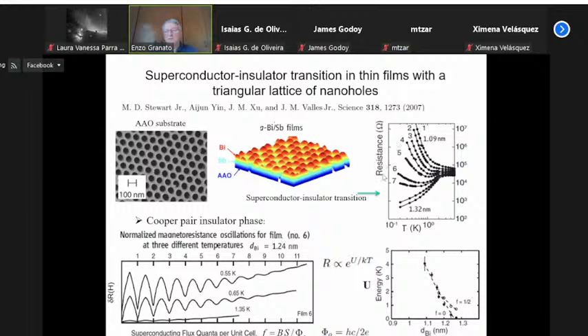Now, on the insulating side, for example sample 6, if you look at the resistivity as a function of magnetic field, this figure in particular is for zero field. If you now apply a field and look at the resistivity of the sample in the insulating phase, you see that this resistance oscillates. The oscillation has a period of one flux quantum per plaquette. You can translate this in terms of frustration or filling factor, if you wish, which is the flux in the unit cell of the array divided by the quantum flux. And the quantum flux here is the quantum flux of the Cooper pair. Therefore, this oscillation as a function of magnetic field has a period equal to the quantum flux for a Cooper pair, indicating that this insulating phase is actually a Cooper pair insulator.